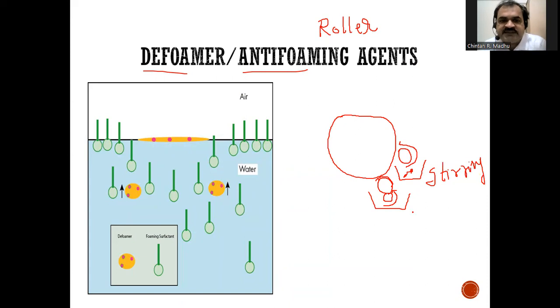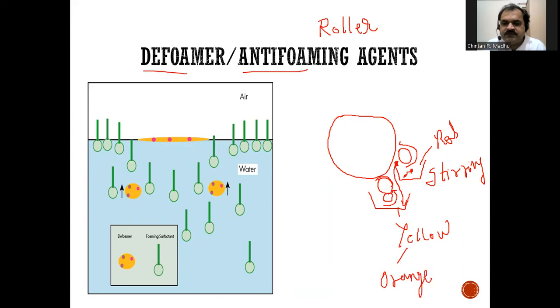Due to the presence of surfactants, that is the wetting agent and solvent, these pastes will generate foam, and that foam will come out here, and at one moment it will drop here. So if you are working here with a red color and here with a yellow color, after foaming, this red color will come to the yellow color and create orange.